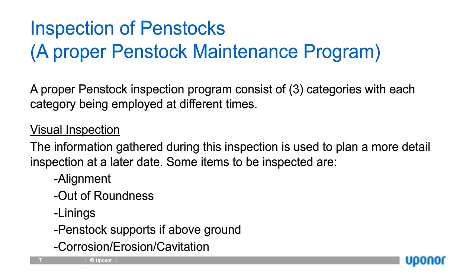Typically, as you're aware, in penstocks, the 2 areas that we're really concerned with is at the inlet, just at the pondage area, where I have a transition or a bend, where I have high turbulences. That's typically where we see a lot of the wear or erosion or thinning. And also at the bottom of the penstock, when I have another transition or another elbow, which again kicks up a higher turbulence. Those are the 2 main areas that we're typically concerned with, but also I can have corrosion and erosion along the pipe as well.